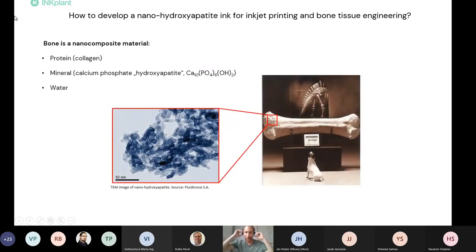So basically, to mimic bone tissue, one needs to first understand the natural constituents of bone. From the literature, it is known that bone is a nanocomposite material consisting of hydroxyapatite nanocrystals embedded in a collagen matrix. So bone consists in its macroscopic constituents of collagen, hydroxyapatite, and water. And we are using rod-like nanoparticles to formulate ink formulations because hydroxyapatite appears as rod-like or plate-like crystals in bone.